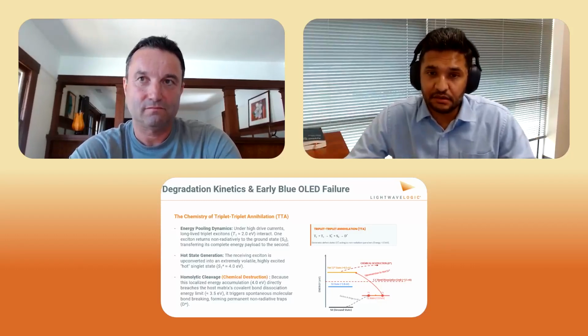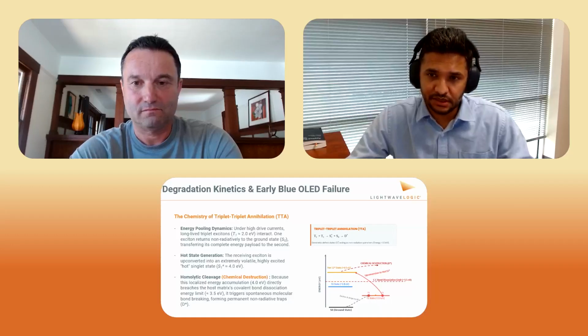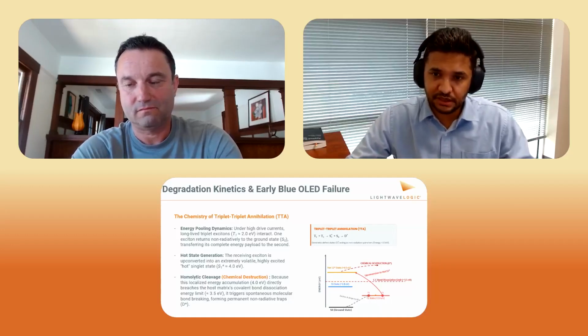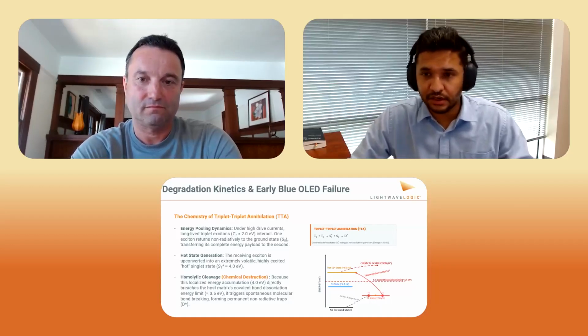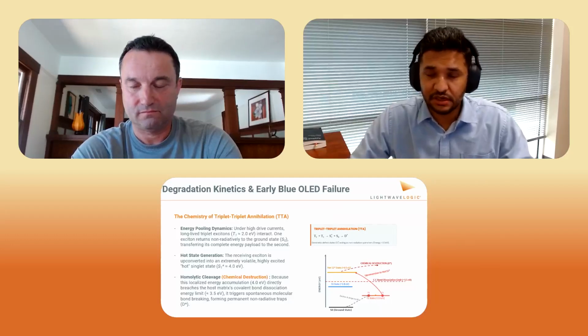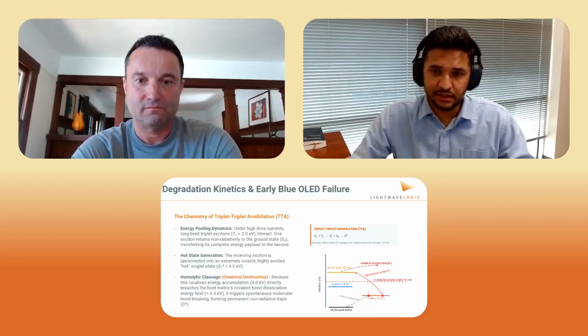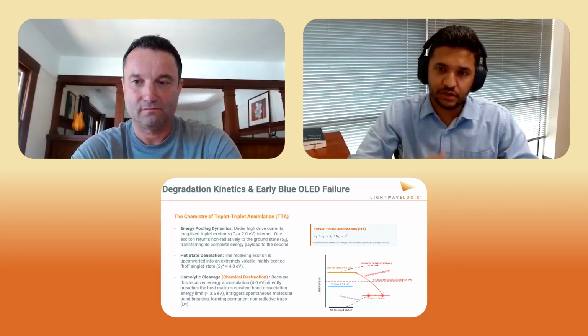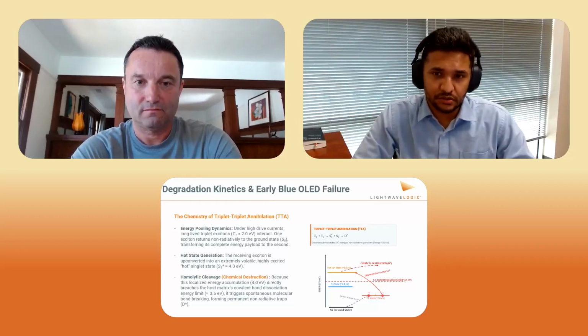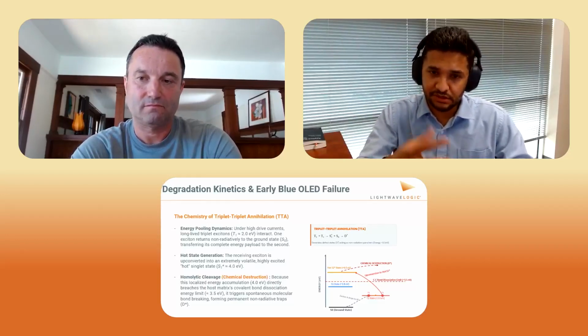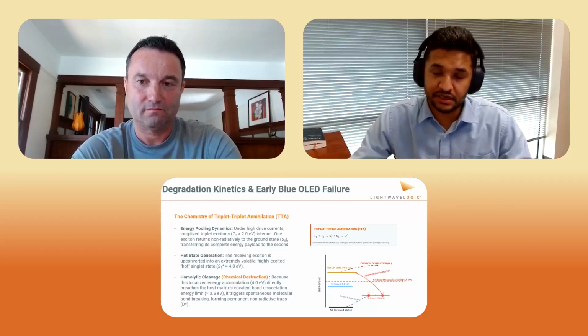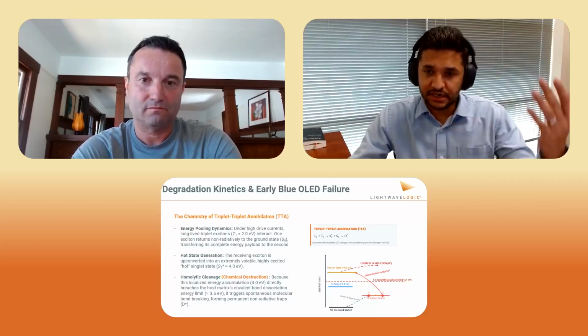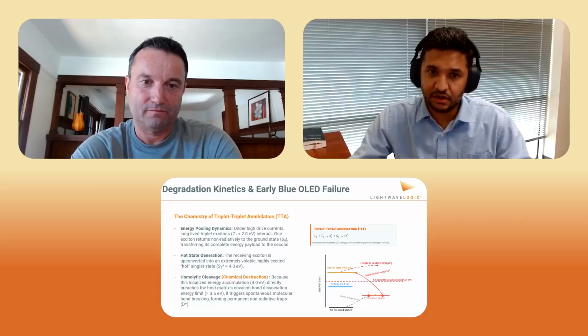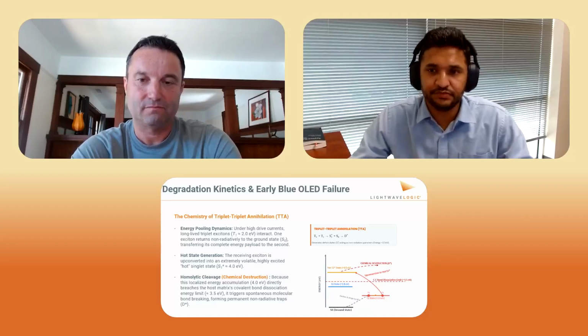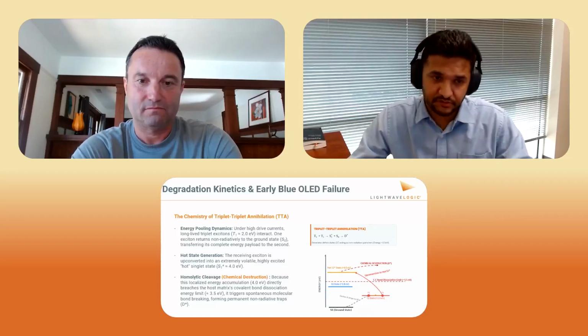The way they engineered around it was very clever. What they did is they introduced another material, and they call it an exciton scavenger. They put it in tandem layers in a vertical stack, and it absorbs these long-lived triplet states. So the population never gets so high that you get hot states that break the bonds. So that's how they engineered around this particular fail mode.